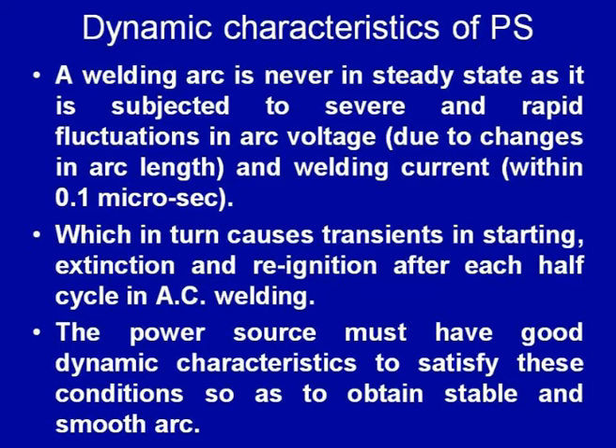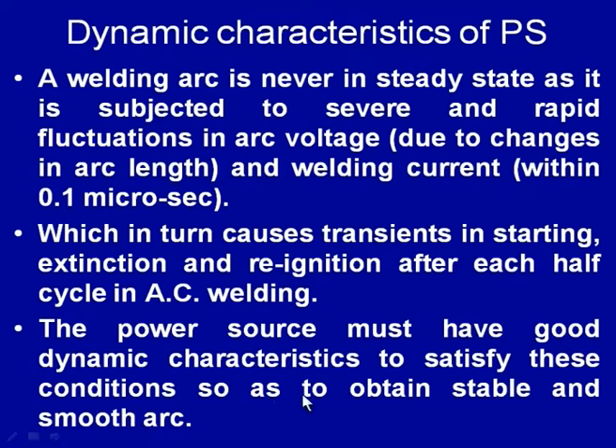As we know, the welding arc is never in a steady state, as it is subjected to severe and rapid fluctuation in arc voltage, and this mainly happens due to changes in arc length and welding current. These things change very rapidly, say within 0.1 microsecond. These changes cause transients in starting, extinction and reignition after each half cycle in the case of AC welding, and the power source must have a good dynamic characteristic to satisfy these conditions, so as to obtain a smooth and stable arc.